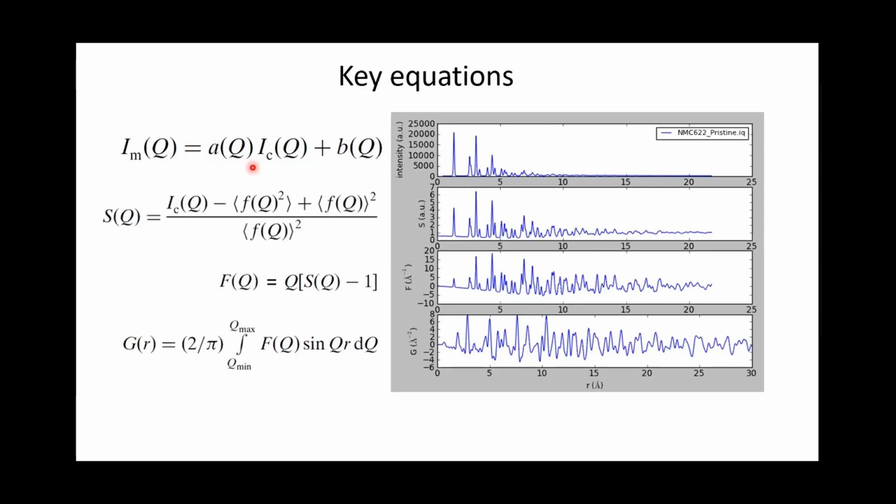And also, the X-ray is polarized, so we need to understand that. In principle, synchrotron X-ray has a polarization factor of 1, meaning the electromagnetic wave is constrained to one plane, not dispersed in all planes. But the true polarization factor for synchrotron is typically about 0.95 to 0.99.